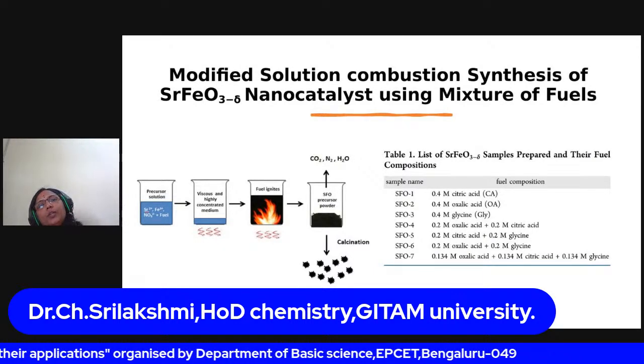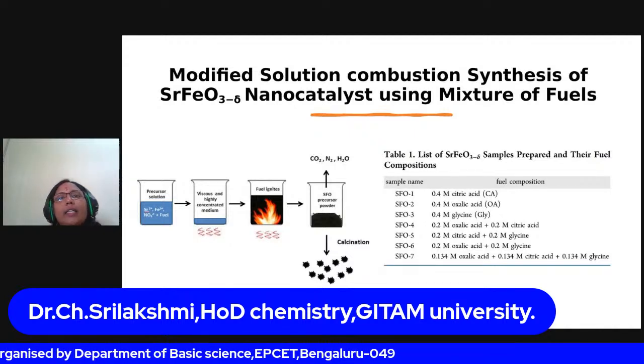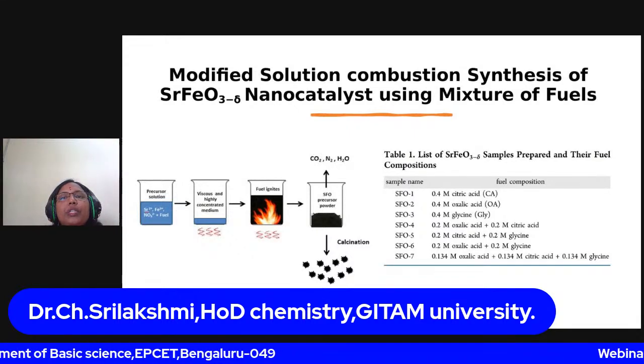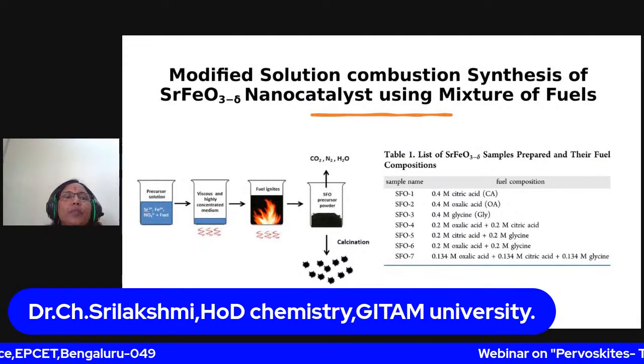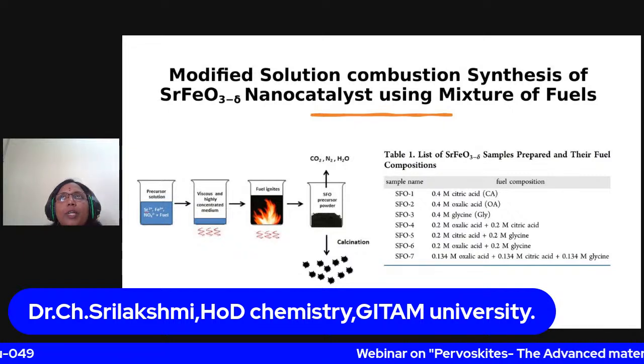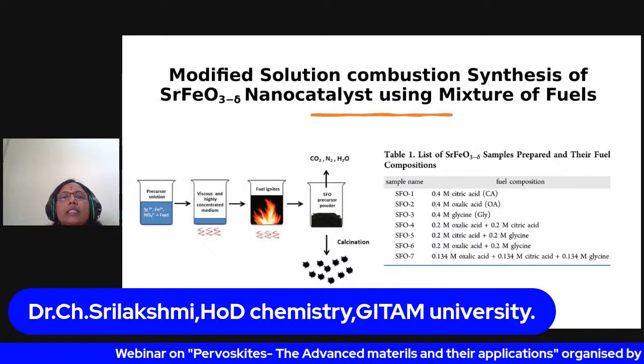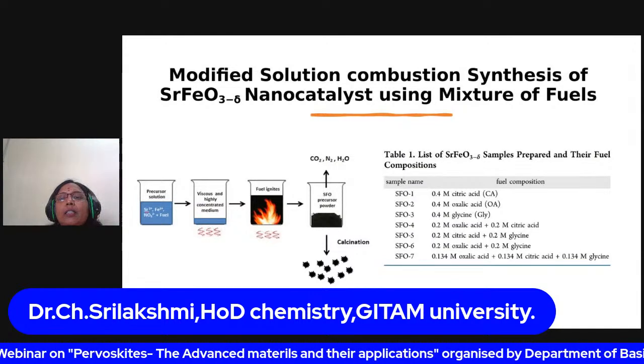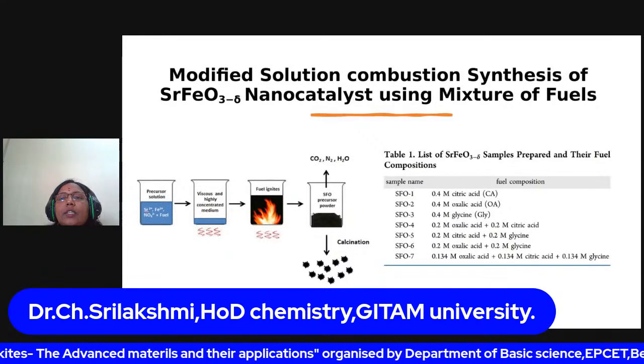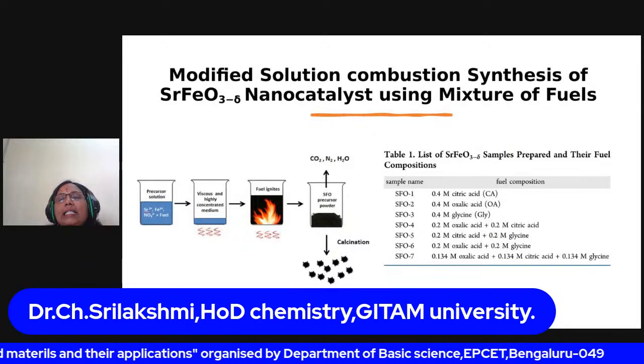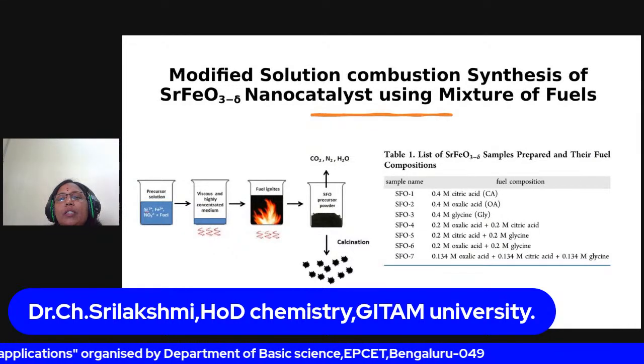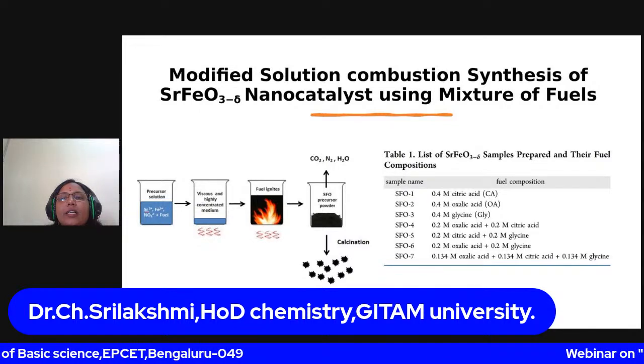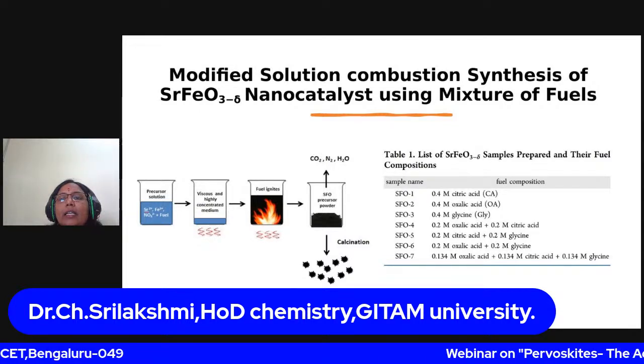This is, as I discussed before, modified solution combustion synthesis. Instead of a single fuel, I have taken a mixture of fuels. What are the fuels I used for the synthesis of strontium ferrite? Citric acid, oxalic acid, and glycine. The combinations are citric acid with glycine, oxalic acid with glycine, and a combination of all three fuels.